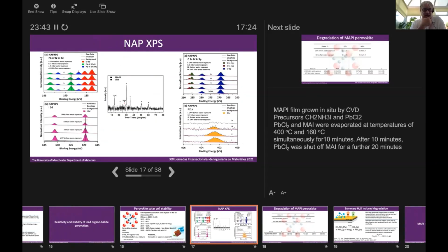So we wanted to try and understand what the key processes are occurring when these things are exposed to water. In this particular experiment, we prepared an atomically clean strontium titanate perovskite material, and we then grew MAPI on the surface. We exposed our strontium titanate crystal to 2 crucibles, one containing lead chloride and one containing methyl ammonium iodide. Methyl ammonium iodide was heated to 160 degrees, the lead chloride to 400 degrees, and we evaporated them simultaneously onto this crystal for about 10 minutes.